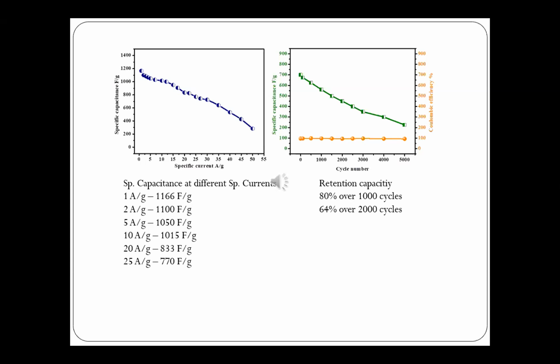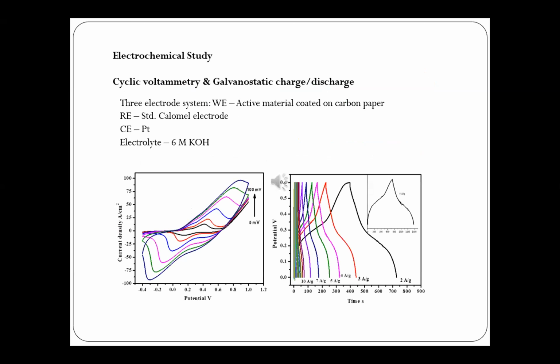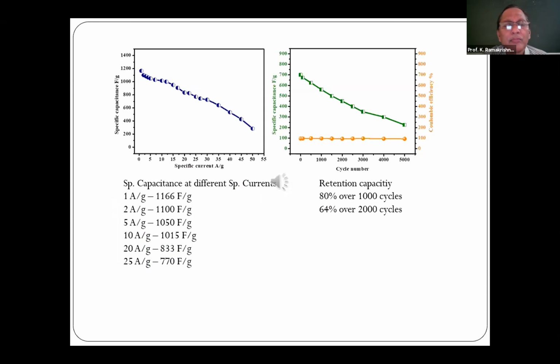From the galvanostatic charge discharge studies, as seen in the previous slide, we can see charge discharge plateaus, which resemble strongly those of the cyclic voltammograms, which pronounce once again that the mechanism is redox reactions, or Faradaic type. At different specific currents I studied the discharge capacities and specific capacitances. At 1 ampere per gram specific current, I calculated a specific capacity of around 1166 farads per gram. At 2 amperes per gram it was 1100 farads per gram, and at 5 amperes per gram it was 1050. At a very high current load of 25 amperes per gram, I was able to get 770 farads per gram, which is very significant.